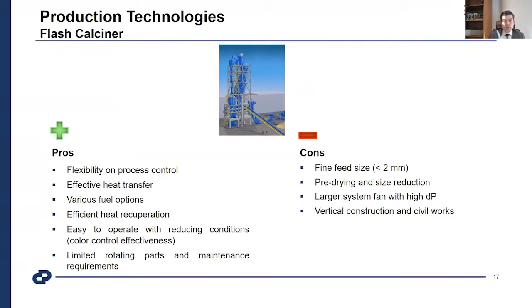Heat transfer is much more effective compared to the rotary kiln because of the fine ground material, so heat transfer efficiency is higher. There are various fuel options available, such as secondary fuels and others. Recirculating the gas can be used, and it also creates flexibility. Heat recuperation is also efficient, and it's easy to operate with reducing conditions because it can be managed. The reducing atmosphere can be oxidized in the top stage or some other place, without any danger or risk to the process.